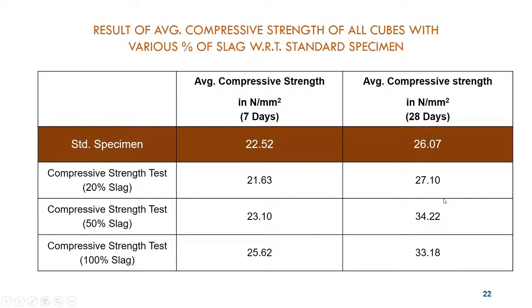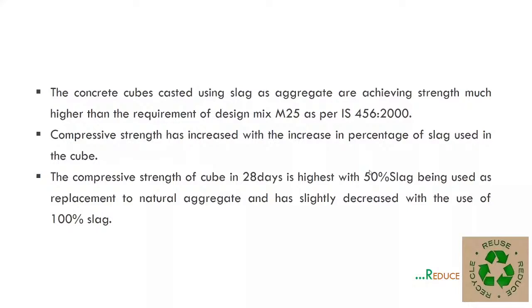Of course, the value was highest for the 50% replacement of the slag, but again, all these values are much above the value which is required for the M25 mix. See, the concrete cubes cast using slag as aggregate achieved strength much higher than the requirement of the design mix M25. The value was highest with 50% slag used as a replacement to natural aggregate. It slightly decreased with the use of 100%, but it is still greater than the value which is required.